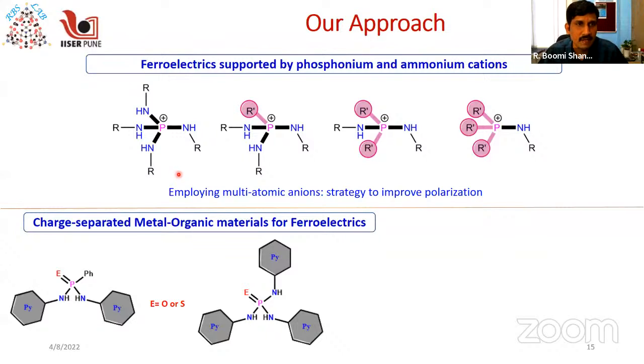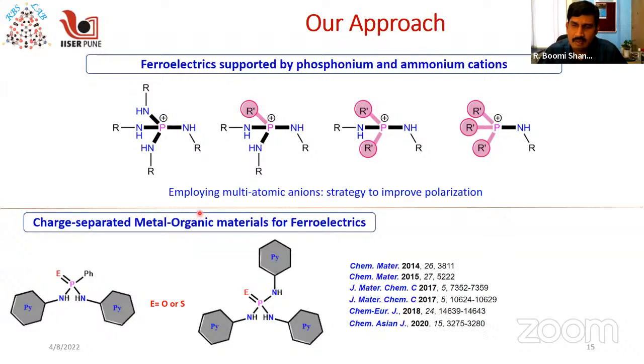In order to reduce the symmetry of the system, we try to judiciously make them heteroleptic. We can substitute one of the amino groups with a simple phenyl group or an organic group, or you can take an all-organic system and substitute them with the amino group. In all the cases, the symmetry of the system gets reduced from tetrahedral to C3v to C2v, which can potentially give rise to non-centrosymmetric molecules with ferroelectric applications. We also made a lot of ferroelectric metal-organic frameworks, called MOFs, using pyridyl functionalized phosphorus ligands, but I'm not going to talk about them in this particular talk.